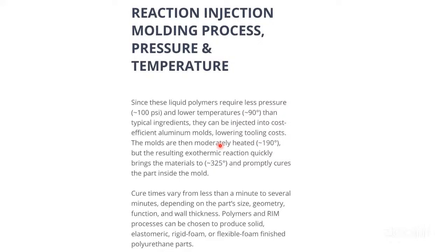See the mold we have seen just now. That is maybe an aluminum mold. Very cheap. Aluminum is cheaper. It does not require very high-grade steel or any other material. Therefore, our tooling cost is lower. The mold is heated up to 190 degrees Celsius. And hence, the exothermic reaction quickly brings the material up to temperature and promptly cures the part inside the mold immediately. Because the heat is developed there inside automatically because of the exothermic reaction.